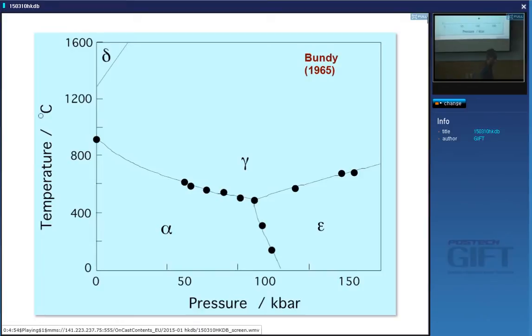Now, even though the tetragonality of alpha iron at room temperature is very small, it has an influence because when you are making a transformer, you get expansion and contraction and magnetostriction. Yeah, you've heard of magnetostriction. When you apply a field, the length changes in a polycrystalline piece of iron. That's a consequence of the alignment of spins and the non-cubic symmetry of the iron. So alpha iron below 760 degrees centigrade is slightly tetragonal. Above it, it becomes cubic.